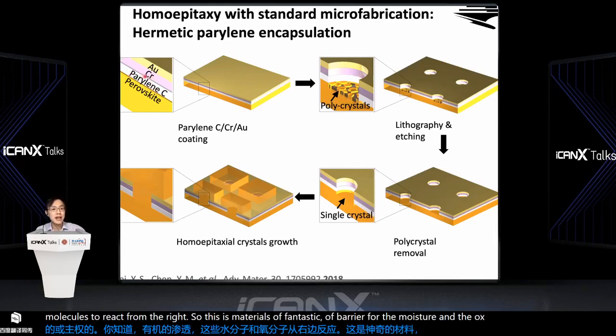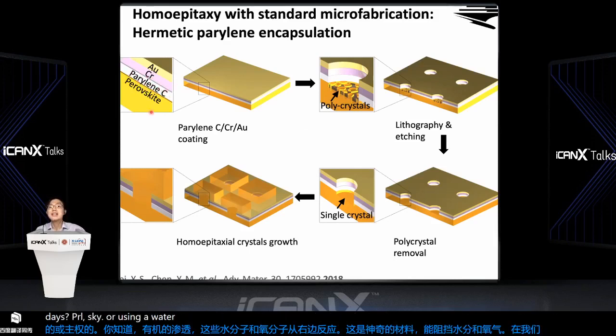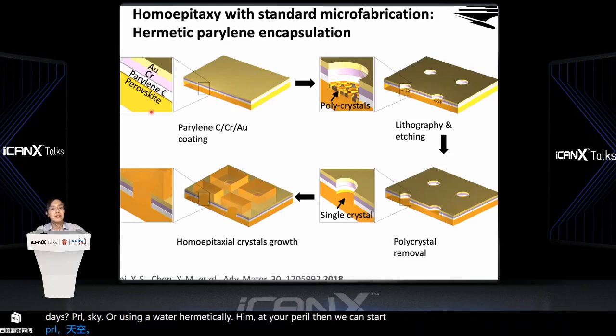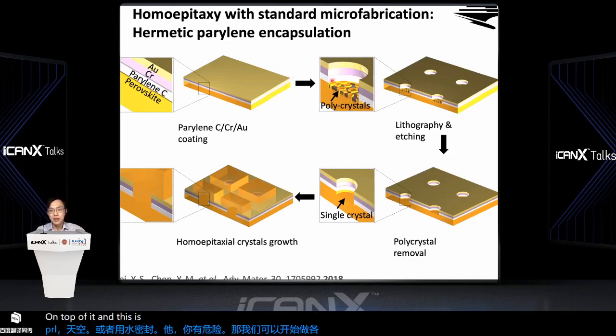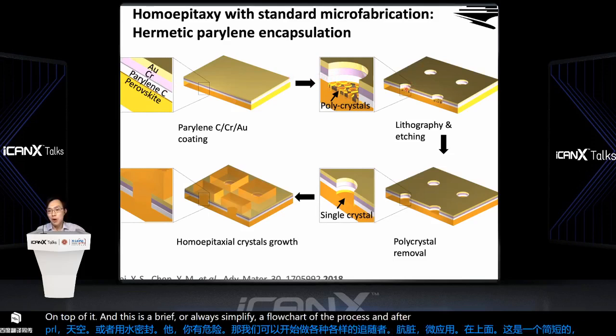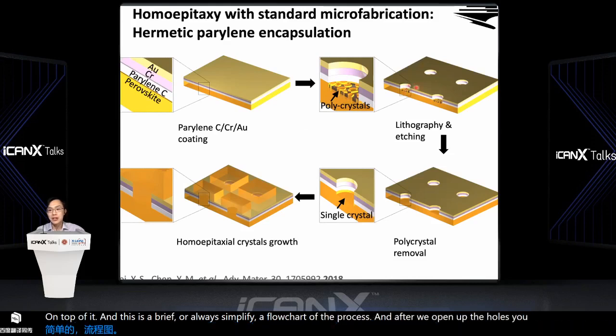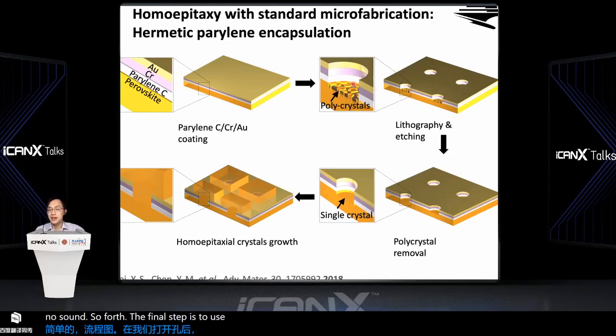And after we protected this perovskite using a very hermetic layer of Parylene C, then we can start to do all kinds of photolithography and microfabrication on top of it. This is a brief, oversimplified flowchart of the process. After we open up the holes using wet etching and so on and so forth, the final step is to use a gas phase dry etch to remove the Parylene C to expose the bulk single crystal perovskite.